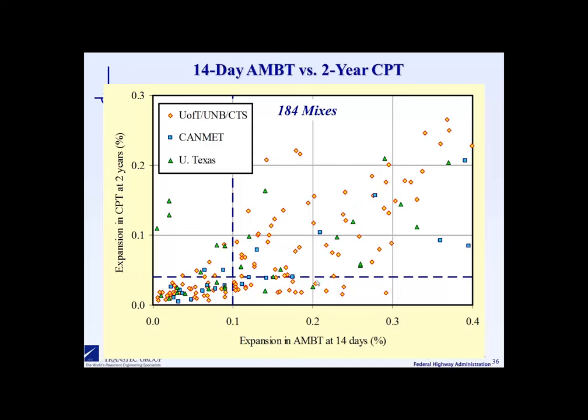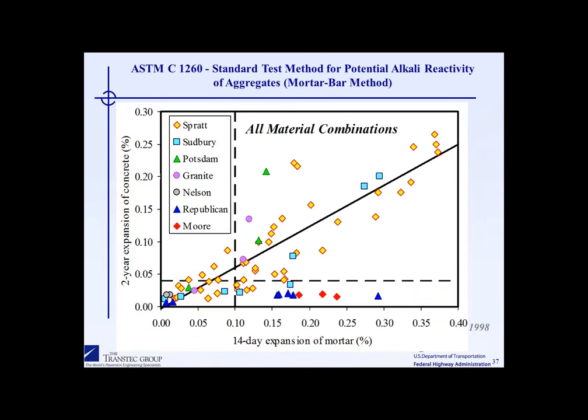But again, we will see cases where we have the bad actors and even the really bad actors that come into play because you're still dealing with the inherent aggressive nature of this test itself. But the good news is if you do have a good aggregate that can be used in the accelerated mortar bar test, you can get reasonable correlation in 2 weeks instead of waiting 2 years. So this is just showing you the relative amount of data that falls in the different quadrants.